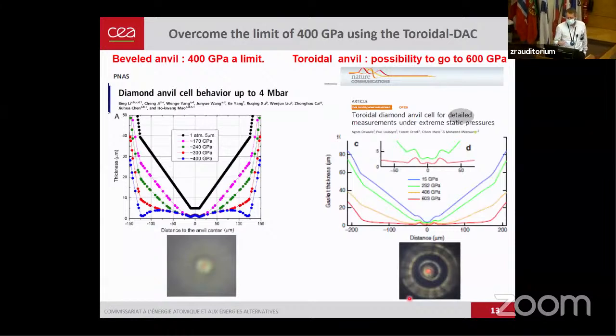Then we have to overcome, so as I showed you, the diamond anvil cell is a standard tool. And usually people are using a diamond that has a bevel shape, so flat diamond, flat tip, and then bevel, polished by polishing the diamond. But despite many efforts and many groups, they are faced that, in fact, reliably you cannot go above 4 megabar with the right scale. And so to go above this pressure,